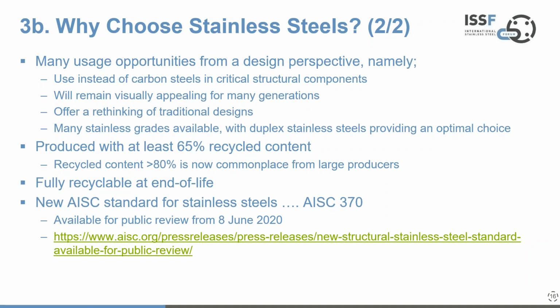It's also fair to say that stainless steels globally are produced with about 65% as a minimum recycled content, and when you actually go to the larger producers, that recycled content is above 80%. These products are fully recyclable at the end of life, so with no loss of material integrity.